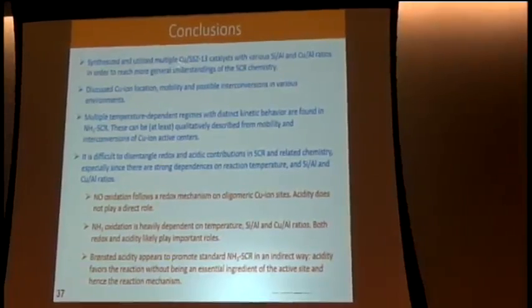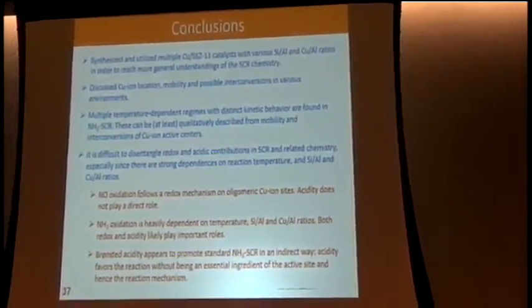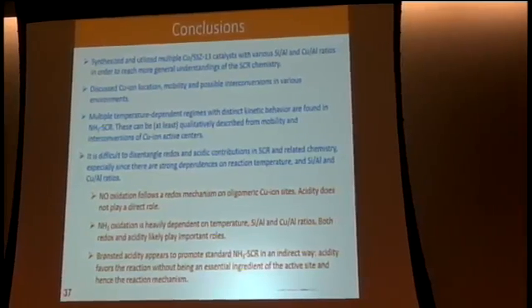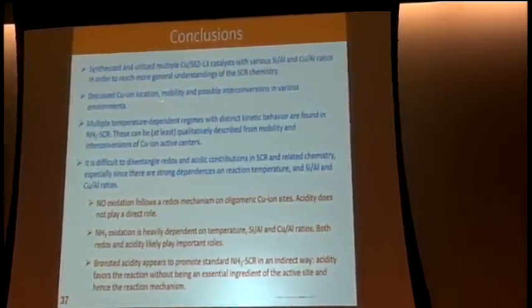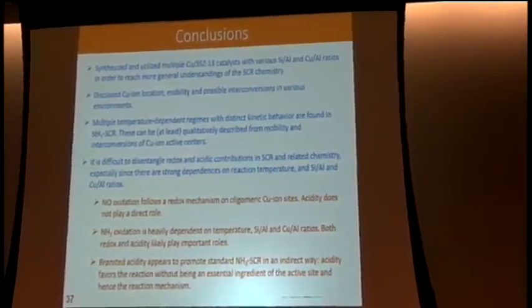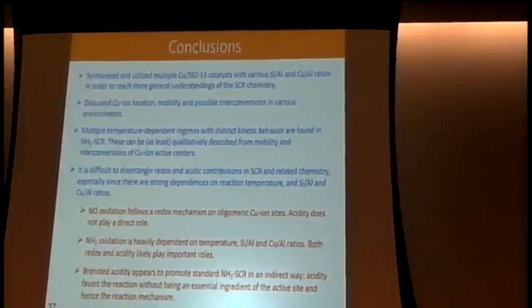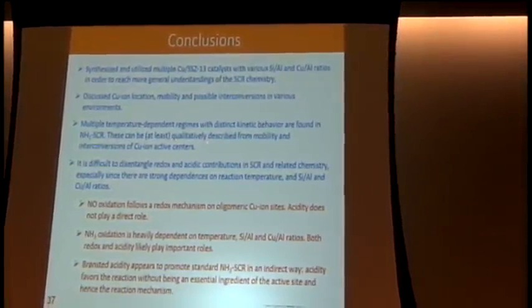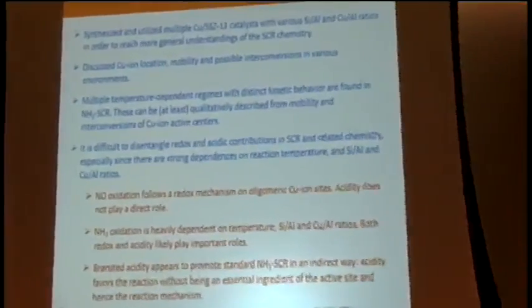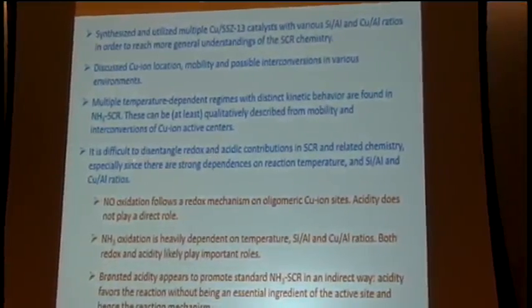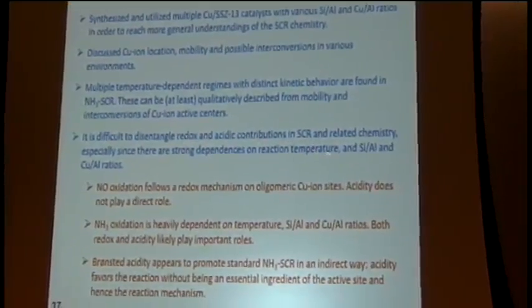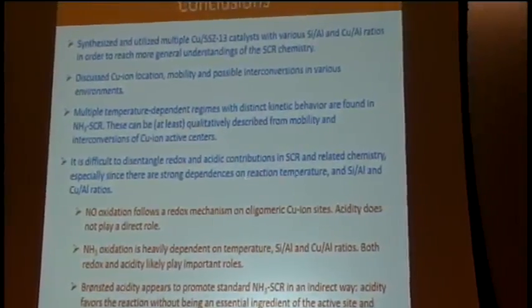I think I covered the following things. We synthesized and utilized multiple copper SSZ-13 catalysts with various Si/Al and Cu/Al ratios in order to reach a more general understanding of the SCR chemistry. We discussed copper ion location, mobility, and possible interconversions in various environments. And we identified different temperature-dependent kinetic regimes during ammonia SCR. At least this can be qualitatively described from mobility and interconversions of copper ion active centers. And finally, it is difficult to disentangle redox and acidic contributions in SCR, especially since there are strong dependences on reaction temperature, Si/Al ratio, and copper loading. But still we can come up with those conclusions.